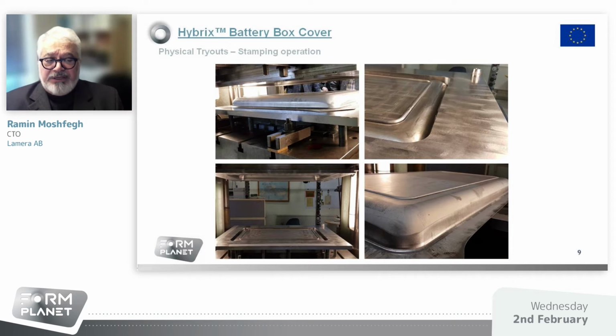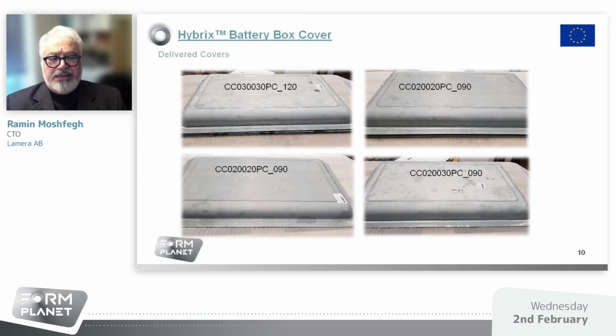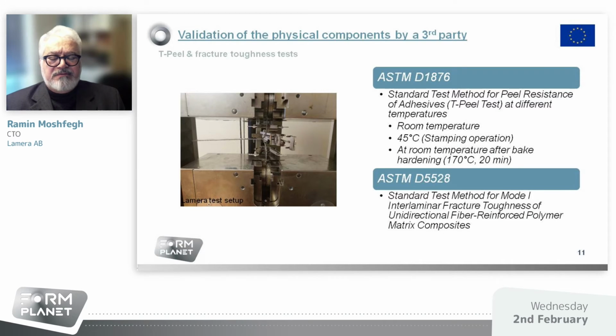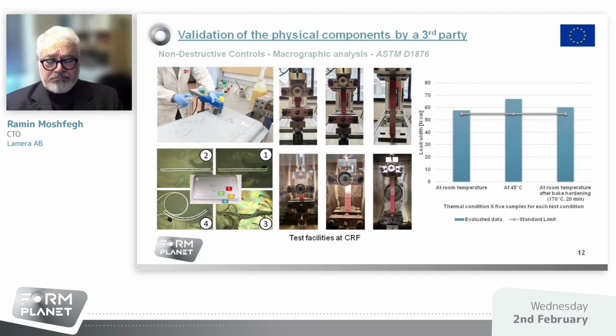This is a tooling setup we have in order to make the physical trial and make a specimen at our company. And here we can see the form part which we delivered directly to CRF. And one of those important validation aspects was to make an ASTM, standard test method, in order to see that the product is feasible after the forming process, before the forming process, and what happened with the material, is it durable or not, actually. And simply CRF take care of that one.